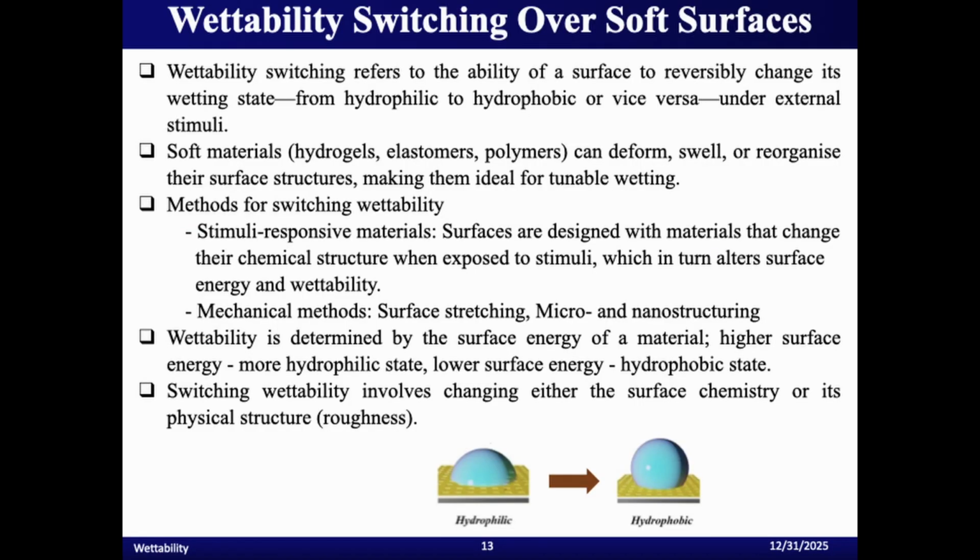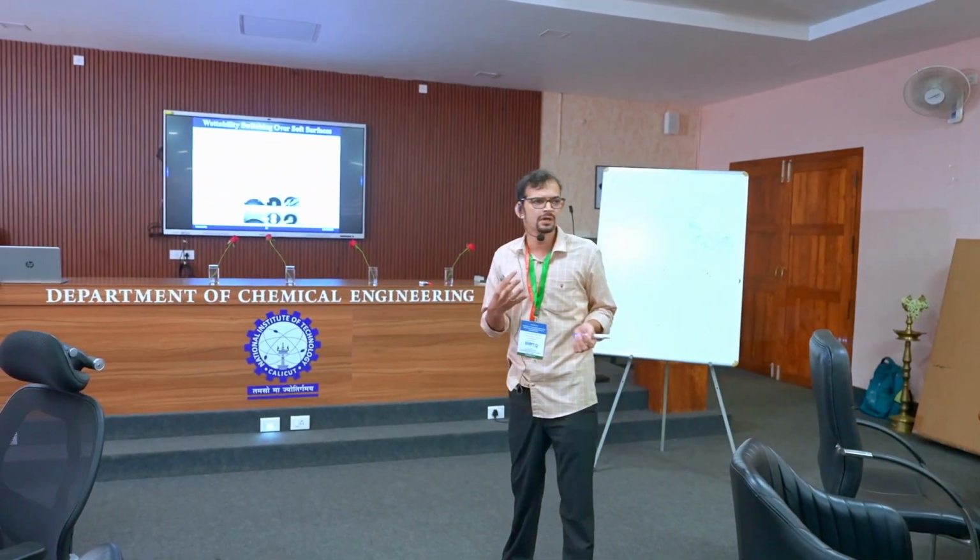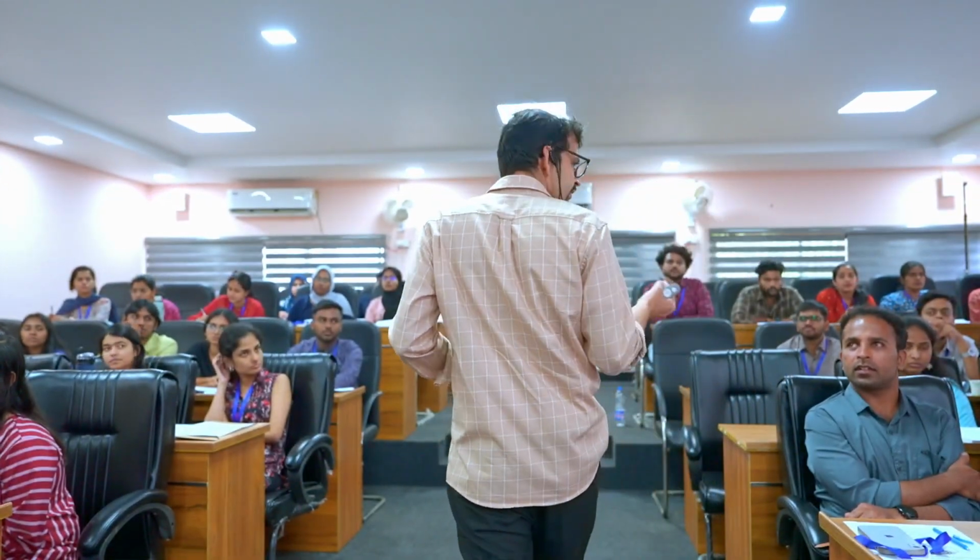Now, these are all not dynamic, but passive. I am coating with some nanoparticles to make these structures. Now what Banu did is very clever. He used a smart polymer surface called PNIPAM, which can respond to temperature. Its LCST is around room temperature, 30 to 32 degrees, so it goes from hydrophilic to hydrophobic. The point is, if you can translate this temperature and connect it with the contact angle,